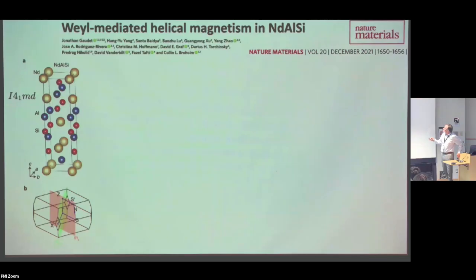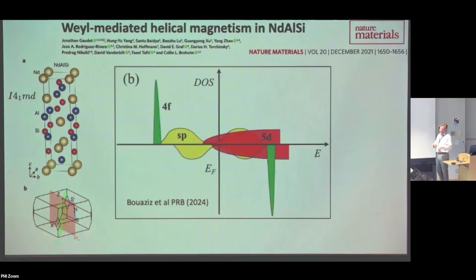And yeah, so let me now begin to talk about neodymium aluminum silicon. So this is the structure. It's a non-symmorphic structure which has a fourfold axis, but it's a screw axis. And so the neodymium sits on this tetrahedral structure in quite an interesting way. So there's no point of inversion in the structure at all. And so it has actually, I should remember the number, I think it's 56 Weyl points in the electronic band structure before the magnetism starts at all. And this was something that Vanderbilt and his group analyzed very carefully.